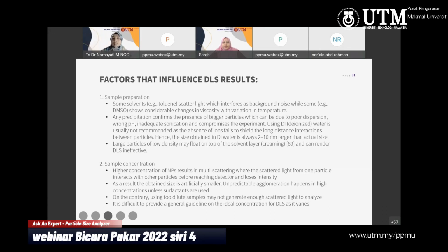So you can just imagine that you are not going to have a good size of particles. Sometimes the particles might have a creaming effect, like floating, and some might be sedimenting. So you have to be very careful. Like I mentioned before, using DI water is usually not recommended, as the absence of ions fails to shield the long distance interaction between particles. That's why you can see that the size might be larger than the actual size compared with the TEM